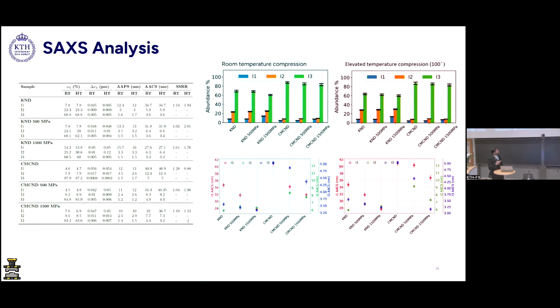We also did the SAXS analysis, similar to project 1, and we could see that at room temperature as well as high temperature, the particle size for Kraft pulp and carboxymethylated pulp, which was roughly on the order of 4 to 15 nanometers, was getting lower in number, lower in abundance. And the cavity size, as we have seen in the SEM images, was getting shrunk. We have seen that trend here too. The cavity size was getting smaller.